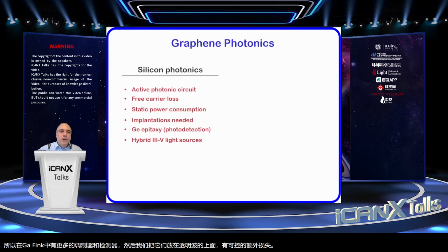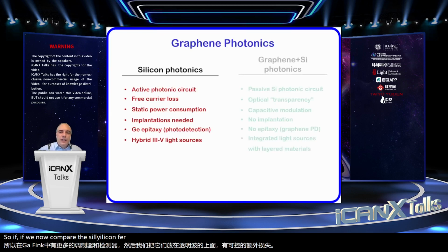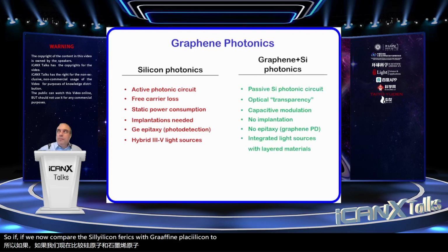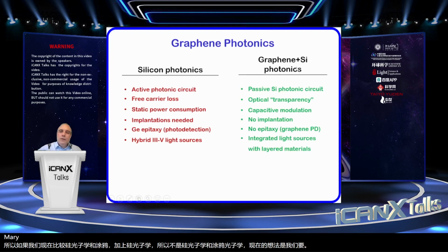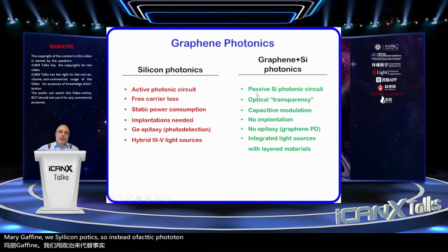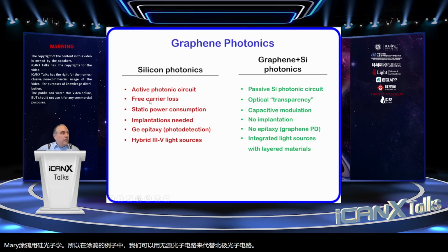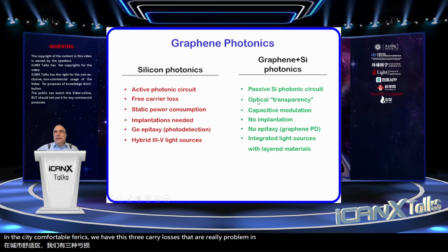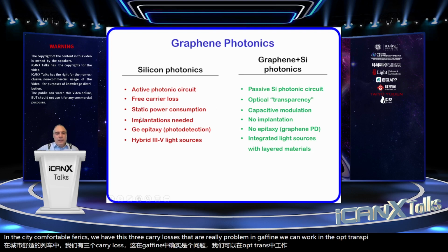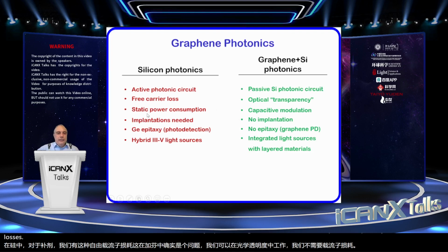So if we now compare the silicon photonics with graphene plus silicon photonics, so it's not silicon photonics with graphene photonics. No, the idea is that we are going to marry graphene with silicon photonics. So instead of an active photonic circuit, we can use, in the case of graphene, a passive one. In the silicon photonics, we have these free carrier losses that are really a problem. In graphene, we can work in the optical transparency. We don't need the carrier losses. In the silicon photonics, we have static power consumption.